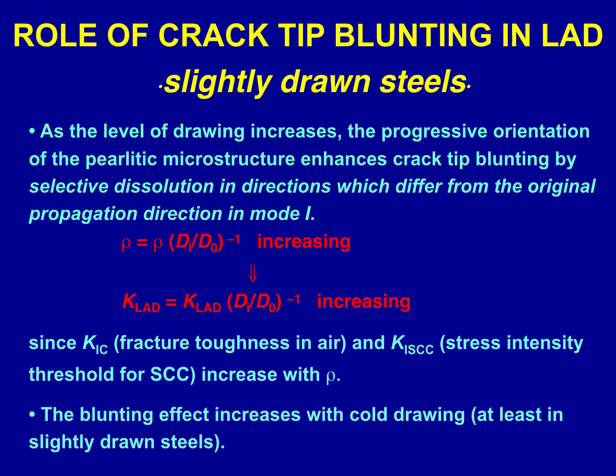The crack tip radius is an increasing function of the level of drawing. Then K-LAD is also an increasing function of the level of drawing, since K1C fracture toughness in air and K1SCC stress intensity threshold for stress corrosion cracking increase with the crack tip radius and thus with the level of cold drawing. The blunting effect increases with cold drawing, at least in slightly drawn steels.